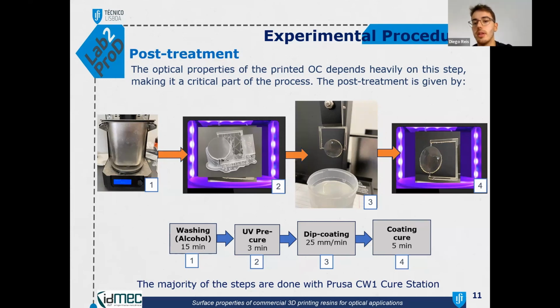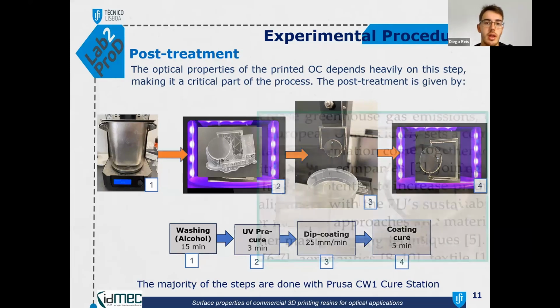Also, beyond this step of coating cure, there's a second step of the cure of the coating, with washing in alcohol in between to remove some sticky surface that could remain after curing. The majority of these steps are done with the Prusa CW1 cure station, which shows that it is a simple process but with many variables. Here is an example of the printed lenses with the coating.